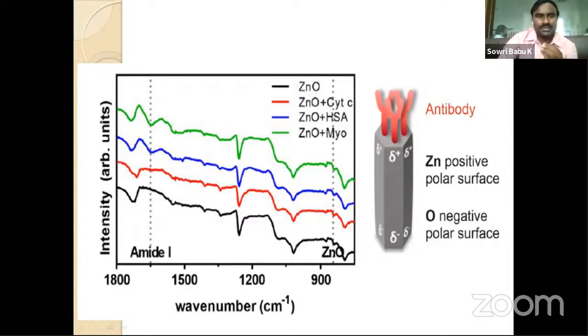that if the isoelectric point of a biomolecule or antibody is less than the isoelectric point of zinc oxide, then it can be directly immobilized on the surface of the zinc oxide. So if the zinc oxide nanorods are vertically aligned, this is how we confirmed whether we can directly immobilize the antibody on the zinc oxide surface or not.